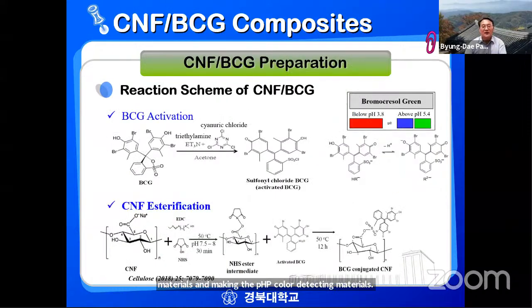So first we worked on the cellulose nanofiber, which is prepared by TEMPO oxidation, with the bromocresol green. But we're not able to use BCG as it is because there's not much reactive site here. And then we activated BCG using triethylamine and cyanuric chloride in acetone, and made sulfonyl chloride groups on here. They change the color because of the protonation and deprotonation, those kinds of acid-base changes like this. And then for CNF, we also need to change the surface of CNF to make it compatible with the BCG together.